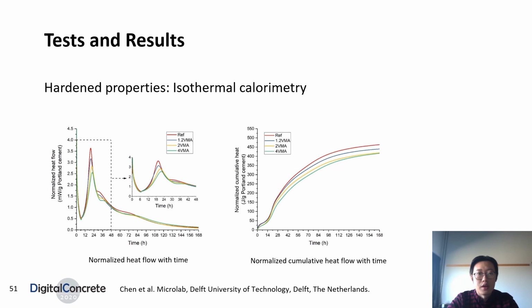The last aspect is about hardened properties. The effect of VMA on hydration was studied via isothermal calorimetry test. It could clearly show that increasing VMA dosage could retard the cement hydration.